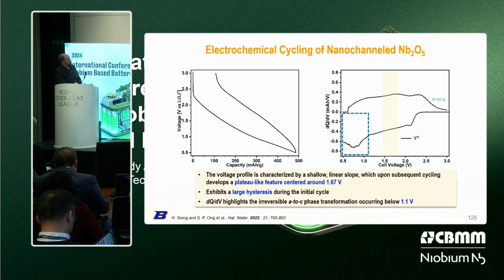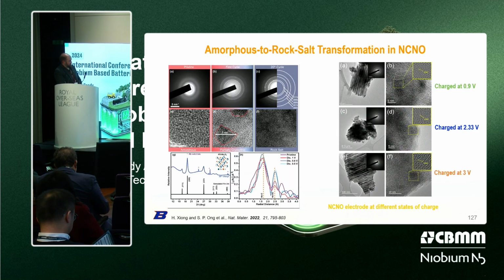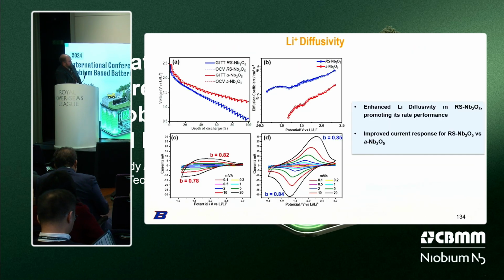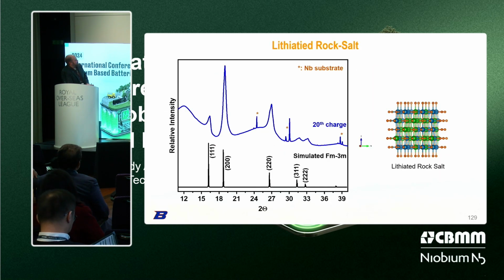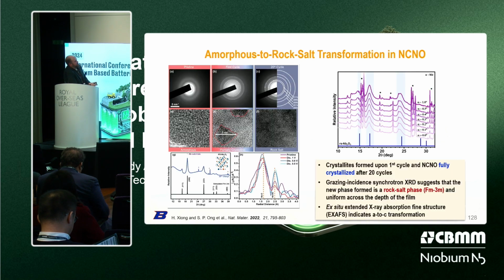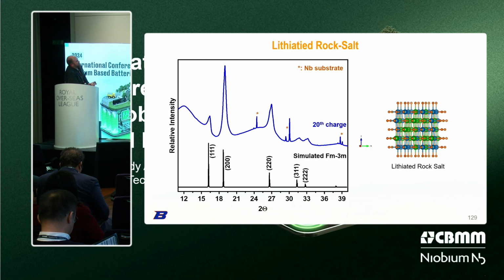So you're saying, did we see any difference between these peaks and which way we're charging and discharging? In the case of the block phases, they're actually unidirectional in terms of how the lithium can get in, and the conductivity is also different in the lateral direction, from the 110 versus 111. Rock salt's a hard structure to get that kind of detail on, as you can see from our XRD. There probably is. We're nanostructured, so we're seeing these nanocrystalline materials in the high resolution TEM. I'd venture to say that probably yes, but I don't know for sure.